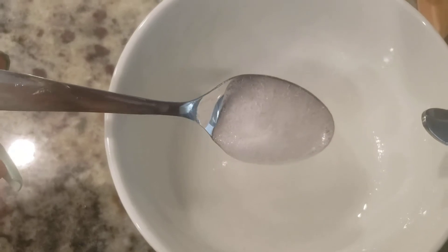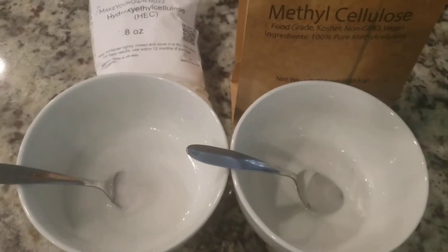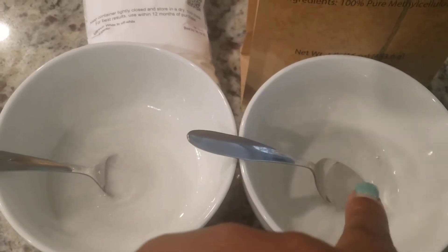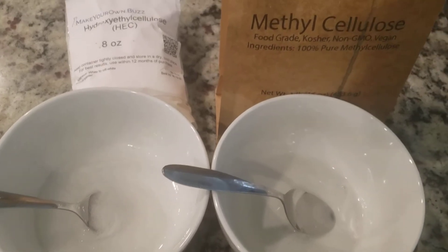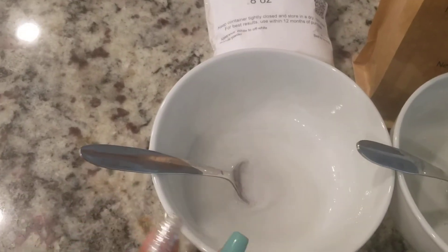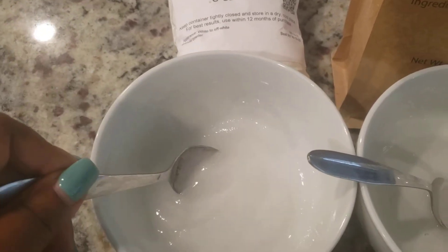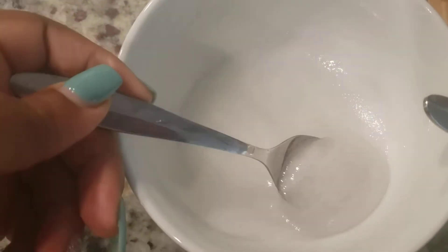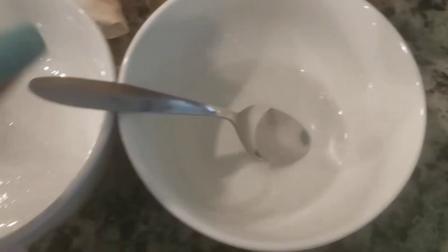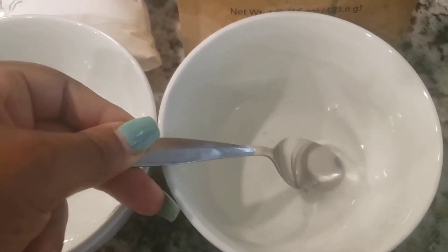However, as you can see, this one is still full of bubbles. I prepared them both last night at the suggested usage rates. For the methylcellulose, you use it anywhere from 0.2% to 1%, and I used that in about 100 grams of water. This one dispersed really, really quickly and easily using the high-shear mixer, and it's now nice and clear — just like it was last night.